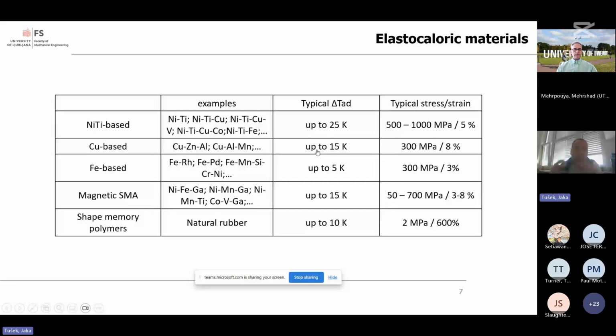The most widely used, both in terms of superelasticity and shape memory effect, but also elastocaloric effect, is binary nickel titanium alloy, which can have very high adiabatic temperature changes up to 25 kelvins upon loading and unloading, but also requires relatively high stress for the transformation, and also has very significant hysteresis, which is a disadvantage. It was, for example, shown that copper-based or magnetic shape memory alloys can have much lower stress required for transformation and lower hysteresis, but the adiabatic temperature changes are somewhat lower.